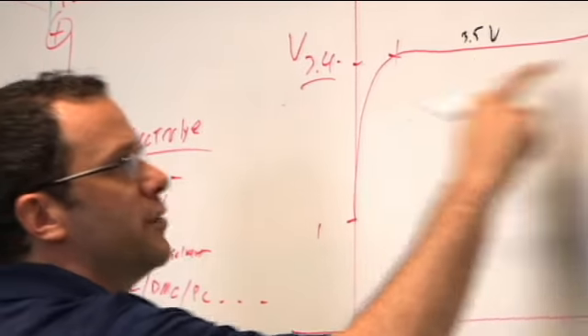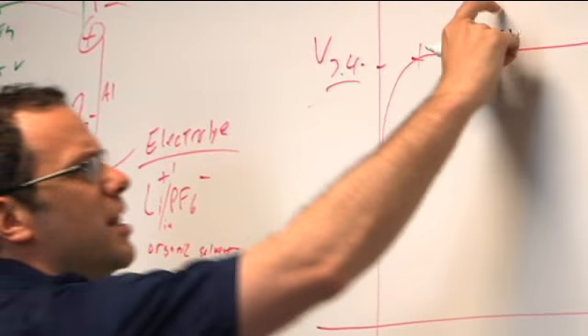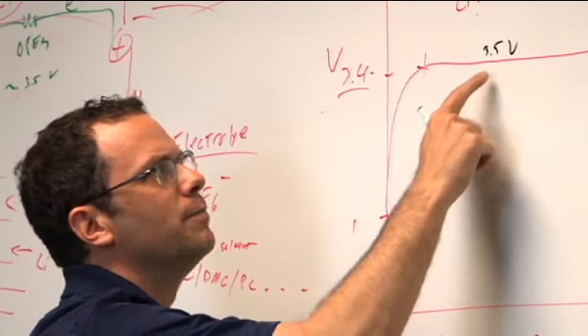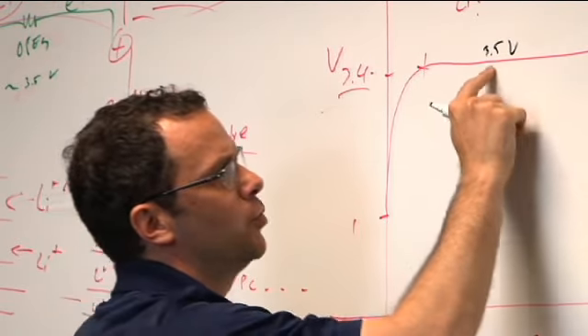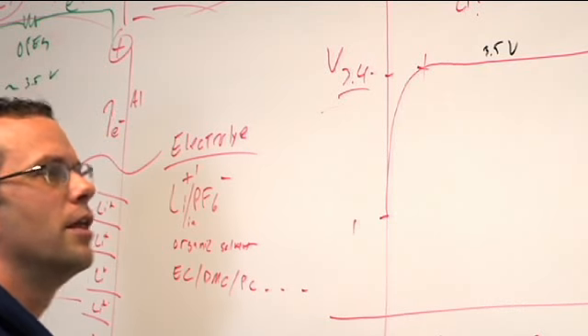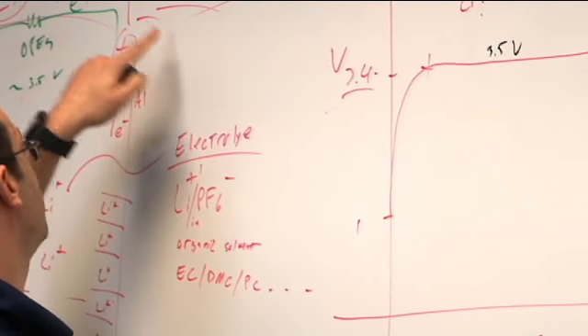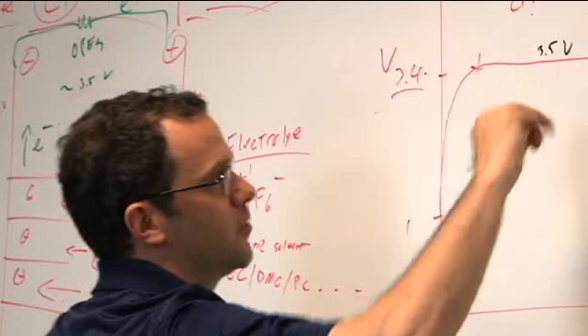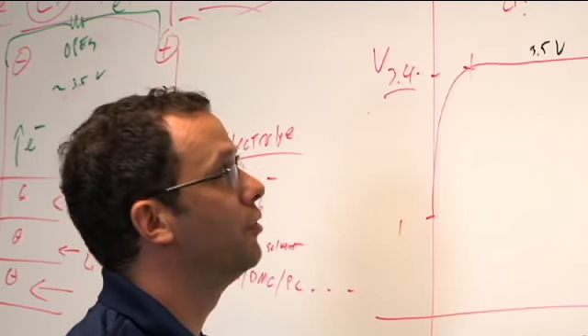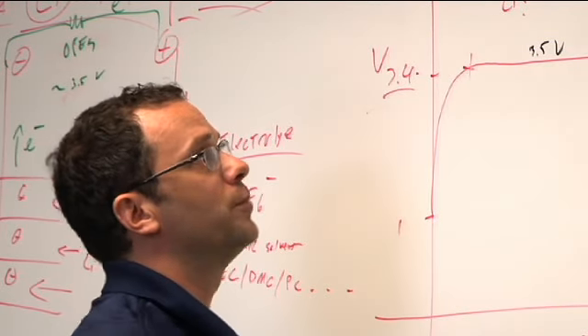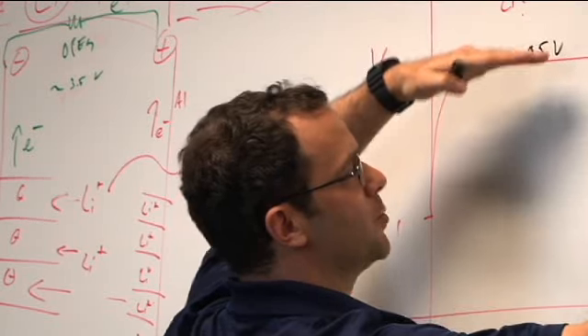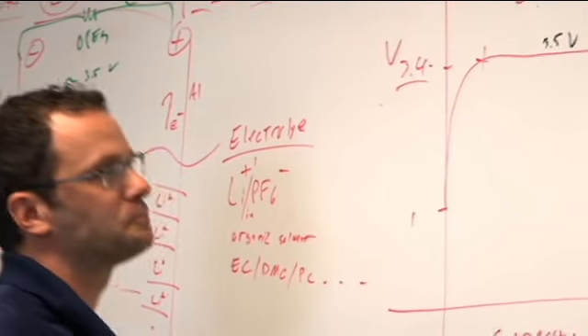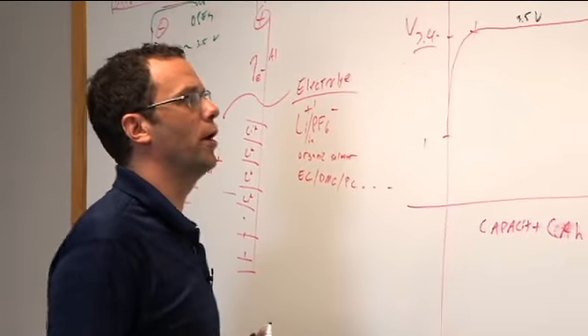These should be very similar if you go at a low rate, and these voltages should be very close. There is a slight thermodynamic penalty to be paid, and that is manifested in the difference between charge and discharge voltage. This phase change between lithium iron phosphate and iron phosphate has a very small but very well-defined energy associated with it. And that energy is the difference between the charge and the discharge voltage. That's going to happen no matter what, okay?